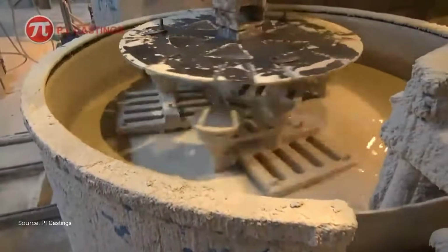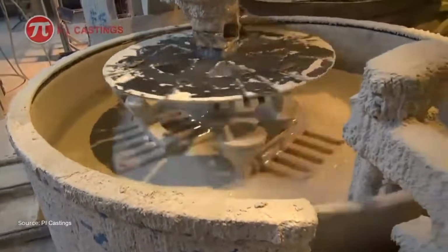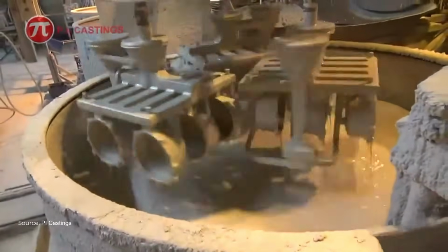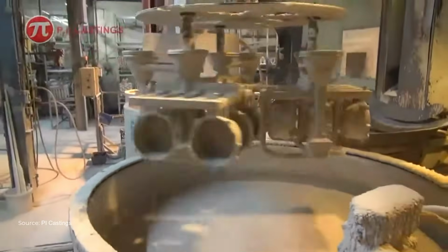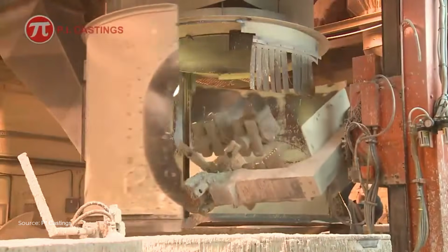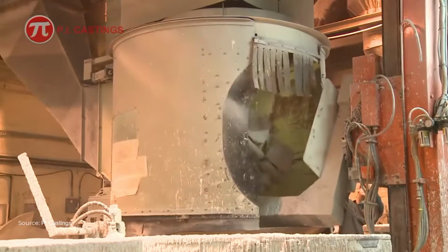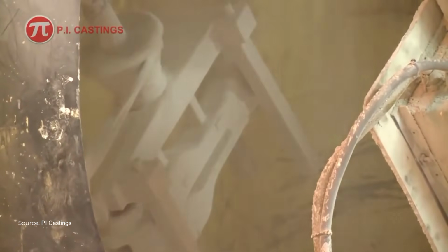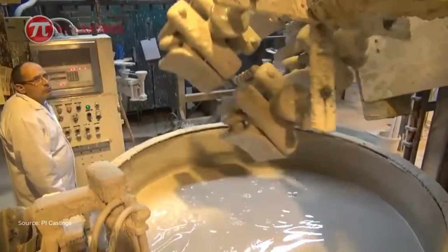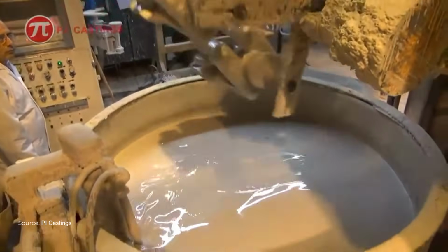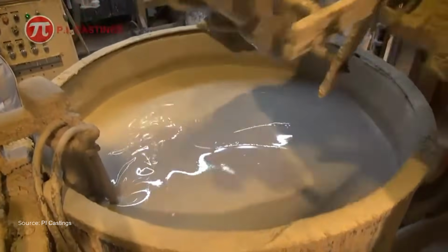Once dried, the wax is removed in a steam autoclave using the lost wax process, and the ceramic molds are fired at temperatures above 1000 degrees C to increase strength and eliminate residual wax. Molten metal is then poured into the preheated molds, allowing it to flow into thin and complex sections. After cooling, the ceramic shell is broken away, and the castings are separated from the feeder system.